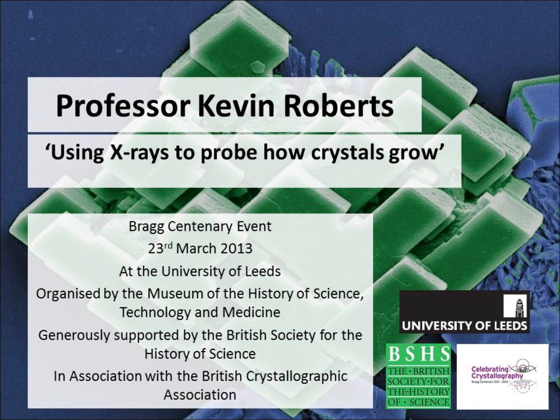Just a couple of examples. Let's go back to the one I mentioned before. Keeping Britain on the move in winter, as we say, diesel fuel contains paraffins. These crystallize and they make these horrible plates. And these are mostly orthorhombic structures, and these plates reflect the fact that the growth along here is very fast and normal very, very slow indeed, because these long chain molecules sit like this. They block the fuel filters.